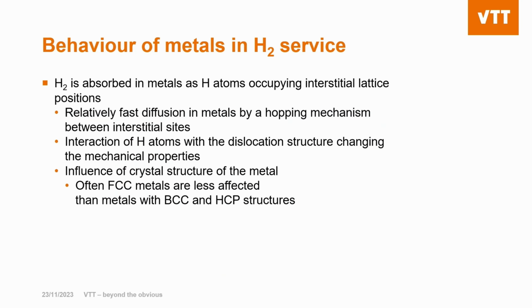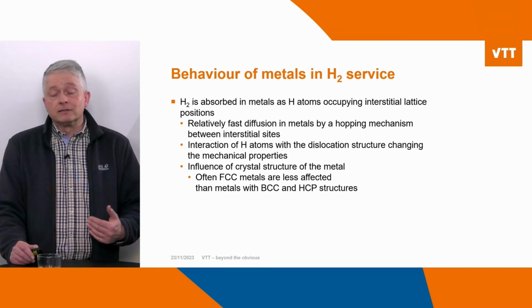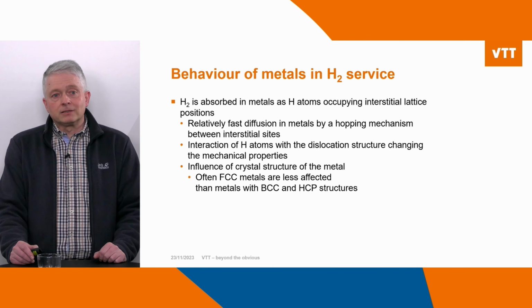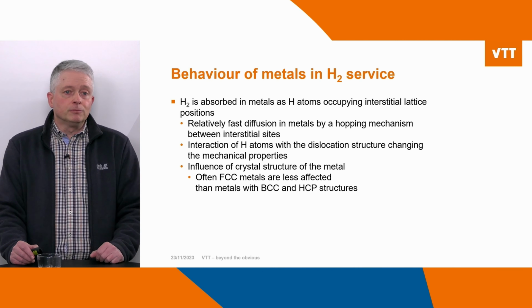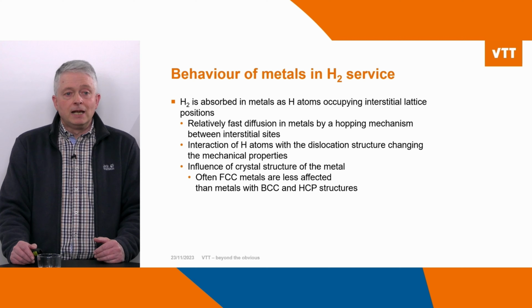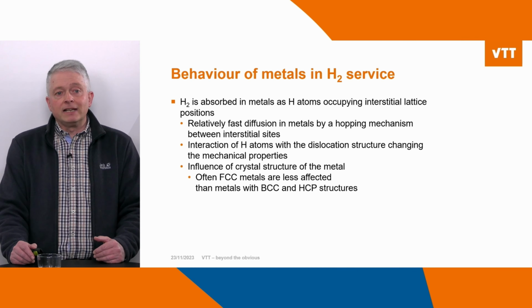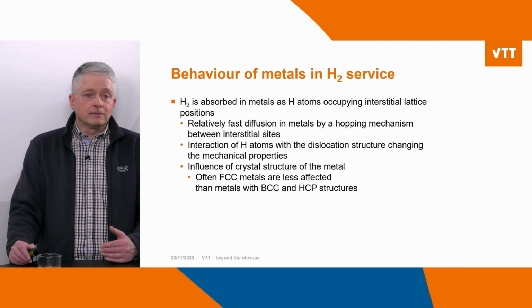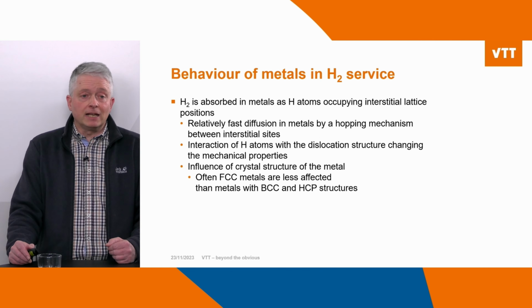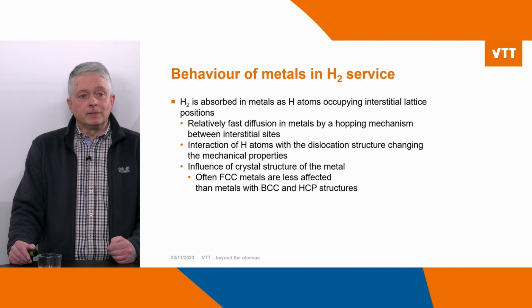And when we look at what hydrogen is doing with our engineering materials, for instance, with metals, we often observe that hydrogen is absorbed in metals as hydrogen atoms, and it is incorporated in the metal lattice on interstitial positions. This enables quite often a relatively fast diffusion by a hopping mechanism between these interstitial sites. Also, the hydrogen can interact with the crystal defects, with the dislocation structure in these metals, and by that quite often changes the mechanical properties of the material.